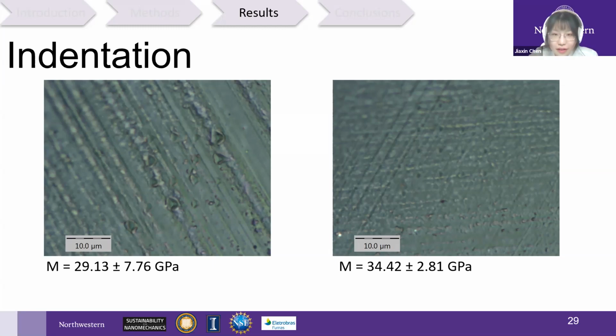Yeah, that is another question we had when we did the experiment. Even though we embedded in air and embedded in epoxy, they should have a similar value. I think another point is that we used different loads for different specimens. We can definitely design a better experiment, but time has passed. For the first one, the air embedded, we used a higher load of 100 millinewton, and for the epoxy vacuum embedded, we used 2 millinewton.